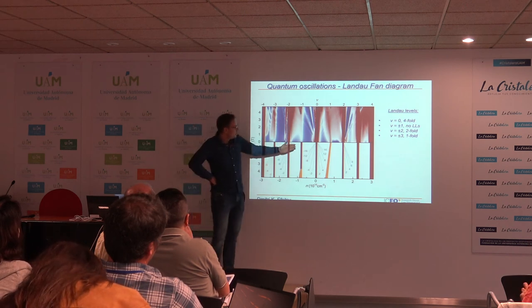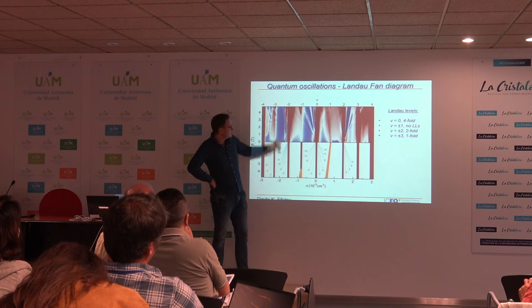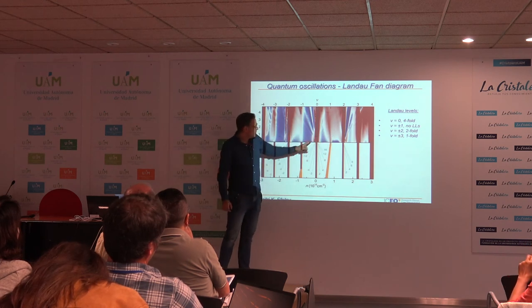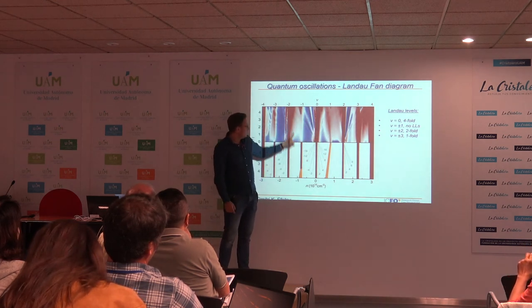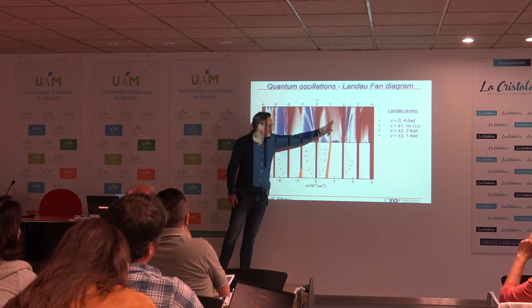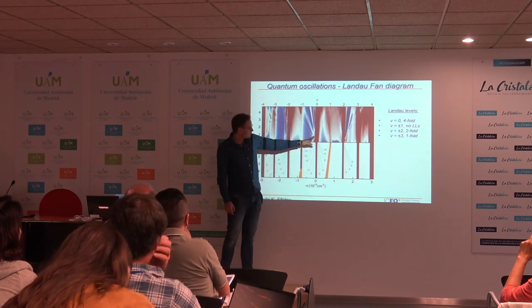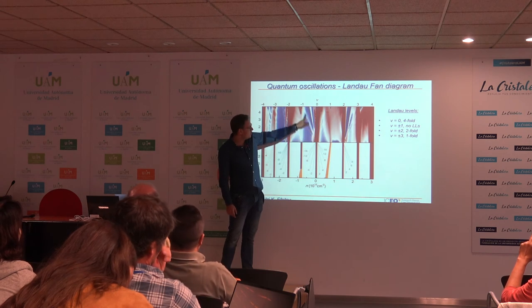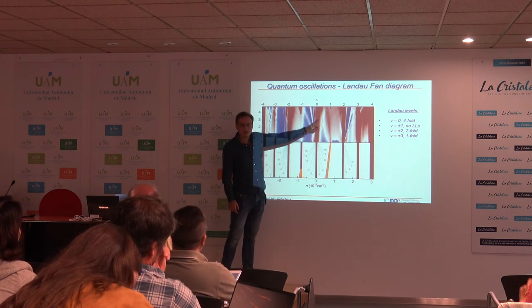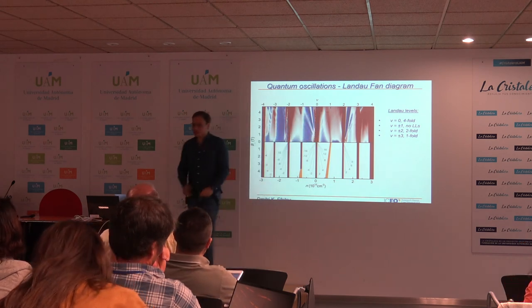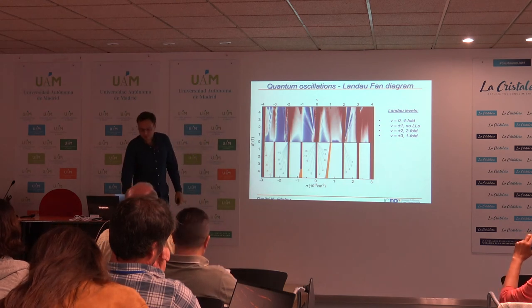And you can see, for example, here is again the band insulator. On that side is a band insulator. This is the charge neutrality point. And these red lines here are the half-filled insulators. And you can see, for example, from charge neutrality, you have these straight lines appearing. And these straight lines are just individual Landau levels in the system.